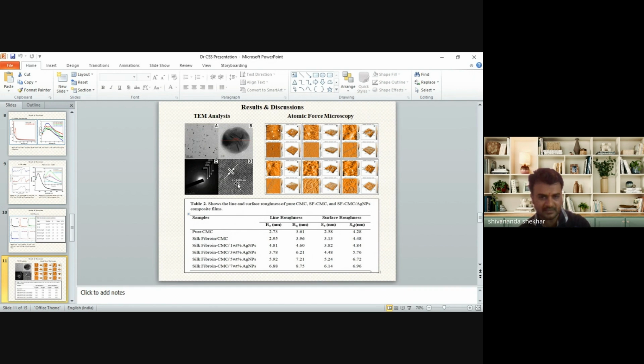And also, we have calculated the d-spacing, the interplanar spacing in the silver nanoparticles. It is found to be around 0.285 nanometer using ImageJ software. And also we have done atomic force microscopy. We have done the 2D and 3D diagrams. So we got to know the peak values, and sharp peaks appeared in these 3D diagrams. This also confirms the formation of AgNPs in the matrix.